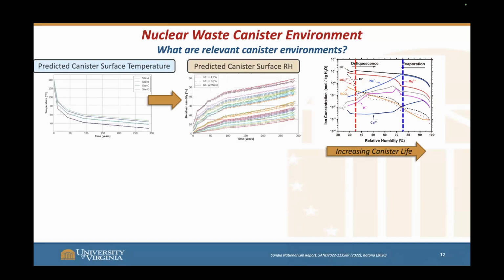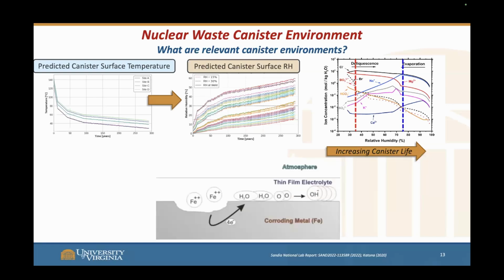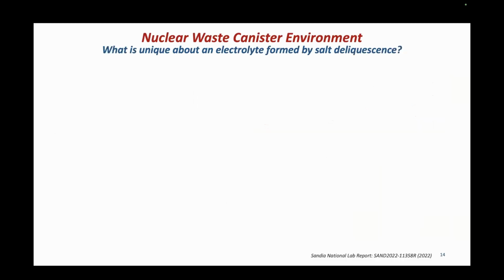Sandia has done quite a considerable amount of work to help determine this environment that's going to be on the canister. They've done predictive modeling to determine canister surface temperature over 300 years as that nuclear waste decomposes. Then that was able to predict the relative humidity. And with this increasing relative humidity on that canister surface, we will start to deliquesce these particles that we are seeing on that canister surface. And with this deliquescence of these particles on the surface, we are then going to start getting a thin film electrolyte that is going to be formed on that canister surface.